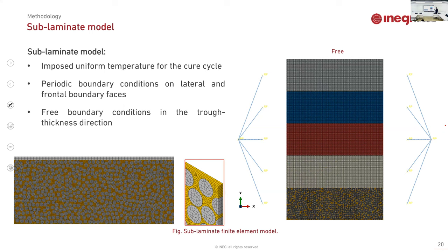More details of the sublaminate. The sublaminate model is a very small portion of the complete thickness. So the finite element model that is considered here is 3D, but it's very thin because I am considering straight fibers in the material. It only has 3 elements in the thickness, and it has periodic boundary conditions in the sides. Each layer is coupled to a master node, and every master node is coupled to a, let's say, a primary node. Okay, the upper and bottom surfaces are free because, as we see in the real material, there are free surfaces, and this is the internal surface of the vessel. There is nothing. The only coupling is to guarantee that the material could be stacked. Let's say this layup is repeated in the side direction and in the normal direction of the screen. Okay. This is the finite element model.